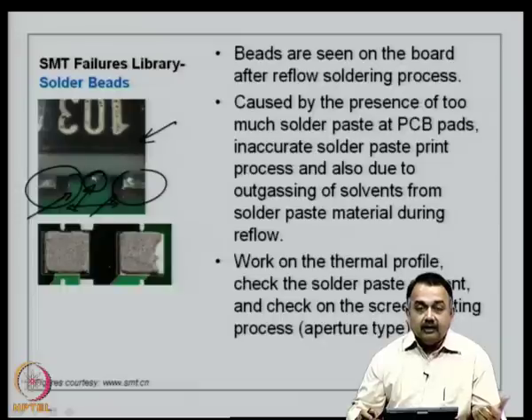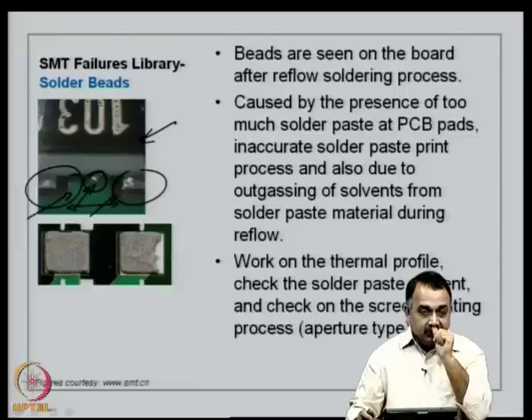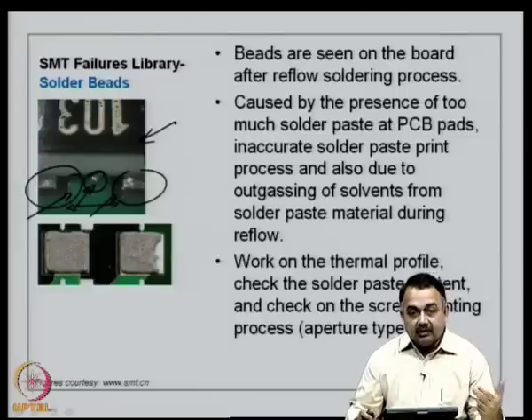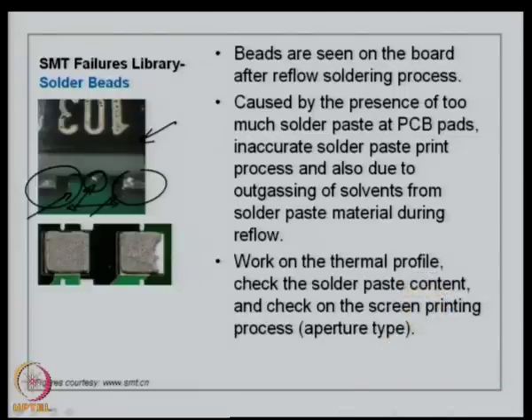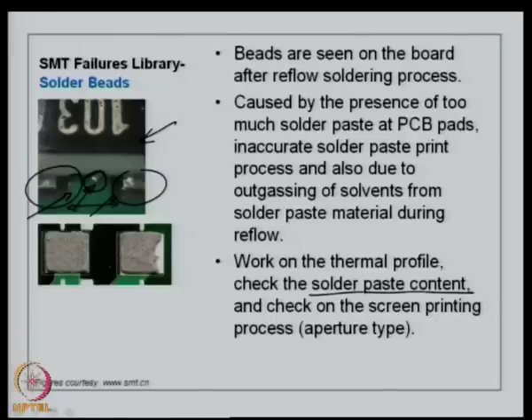Now, again I have to repeat that you have to do very good thermal profiling. So, I am going to show later in this lecture what a thermal profile is and how you take care of and study the thermal profile for different segments. In this case you must know what the content in a solder paste is, what kind of solvents are there, and whether you do gradual heating to remove the solvents. Here you can see in this picture a solder paste has been dispensed on pads, and even before attachment of the component you can see they are not adhering onto the copper pad. Okay.